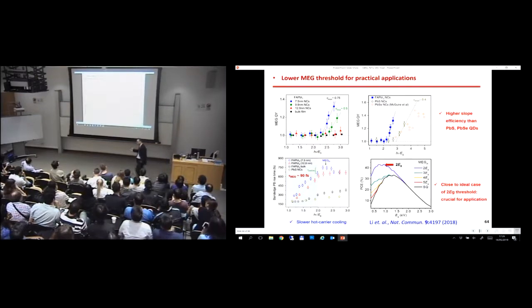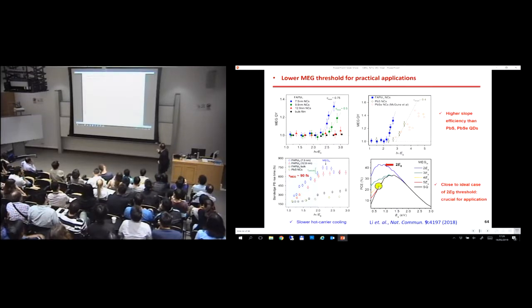Of course, having a slower hot carrier cooling does matter. And the last point I want to say: if you have your threshold closer to about 2 EG, you actually get much higher power conversion efficiencies. So instead of just at 3, if you get anything closer to this 2, you're going to get better conversion efficiencies with this kind of system.